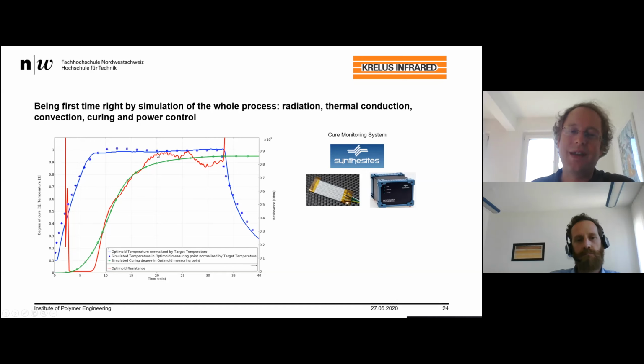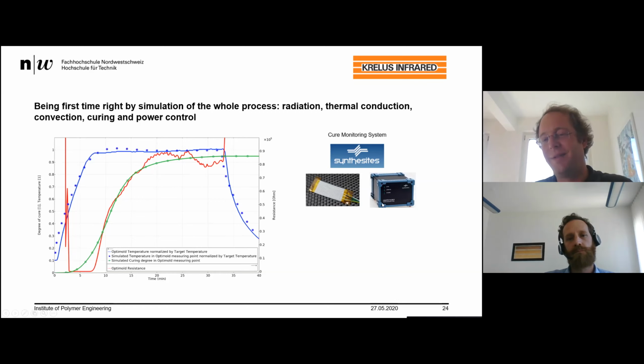So there's a kind of scattering of the cure monitoring result, because we are using the sensors in a temperature range which is not commonly the range where it's normally used. Normally the system is applied to systems around 180 degrees, and I think we used it for the first time for temperatures above 220 degrees. So that's why in this region we have a kind of scattering of the measurement signal.